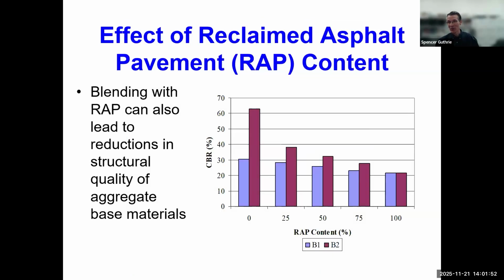But there are also some materials issues that we need to be aware of. And one of them is highlighted in this slide. What you see on the left-hand side is the California bearing ratio. This is a measure of the stiffness of the base material. On the x-axis, you see the RAP content. RAP, in this case, is not a reference to music. It is an acronym for reclaimed asphalt pavement. This is the pulverized asphalt that's mixed with the underlying base material. And in this case, I evaluated from 0% up to 100%. And you see that at 100% RAP, we have a relatively low CBR of around 22.